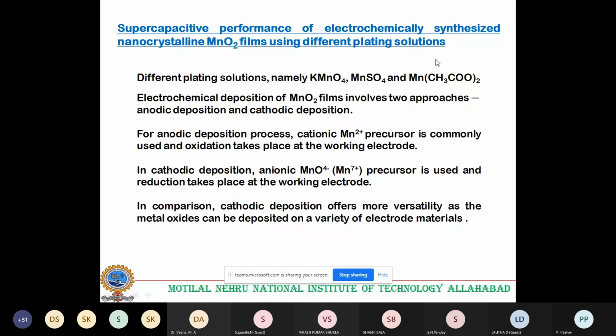Now, these deposited films which we have discussed till now, we prepared from the KMnO4 solution, that is potassium permanganate, using three different modes of electrodeposition. After that, we used different plating solutions: potassium permanganate, manganese sulfate, and manganese acetate. And we prepared the film by all three different modes. We have already completed the work on KMnO4 and found that the film deposited in the potentiostatic mode is the best among all three modes. Similarly, we carried it out for manganese sulfate and manganese acetate.